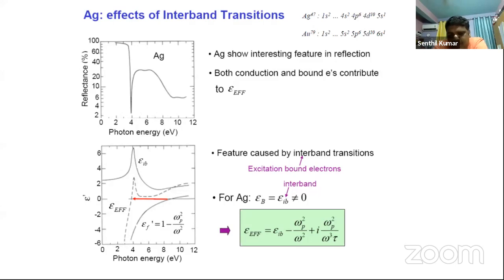People were working on this for quite a long time. The Drude model came in 1900, and until the 1960s people could not understand why the experimental dielectric constant or plasma frequency did not exactly match the theoretical data; there was always some deviation. After various studies, they found that this hybridization is the main issue: interband transition happens and contributes to the bound electron contribution, which is now called the interband transition effect. Once you incorporate that, the experimental data is satisfied.